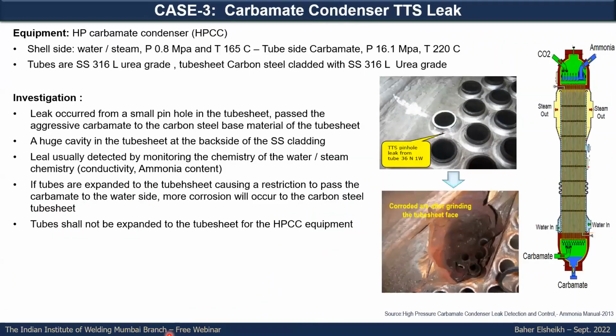This is another interesting case. This is a high pressure carbamate condenser. Some pinholes in one of the TTS joints, a minor one, caused the carbamate from the tube side to pass to the shell side. And if you can see in this photo after removing this part, there is a very big cavity in the carbon steel tube sheet. And this happened in a short time because carbamate is a highly aggressive medium.